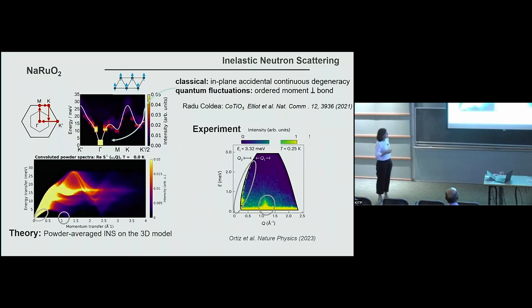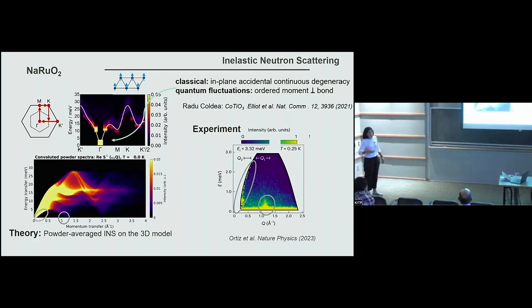first of all, one interesting point is that the classical solution of this model would have an accidental in-plane continuous degeneracy, but the quantum fluctuations are what set the ordered moment perpendicular to the bond, as was also pointed out by Radu in the context of cobalt titanium O3. So this is now the comparison of the model with experiment: this type of model with these ferromagnetic interactions can show this